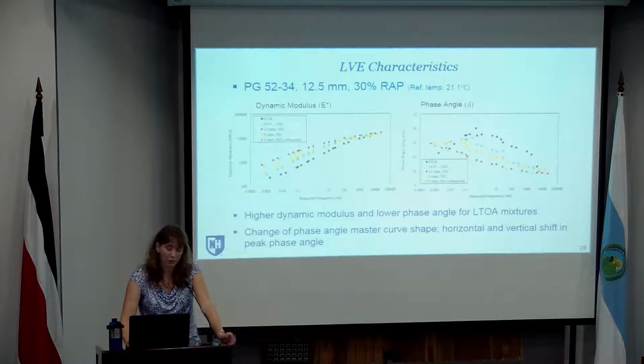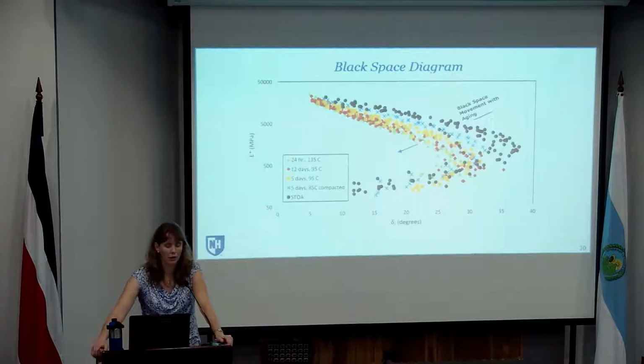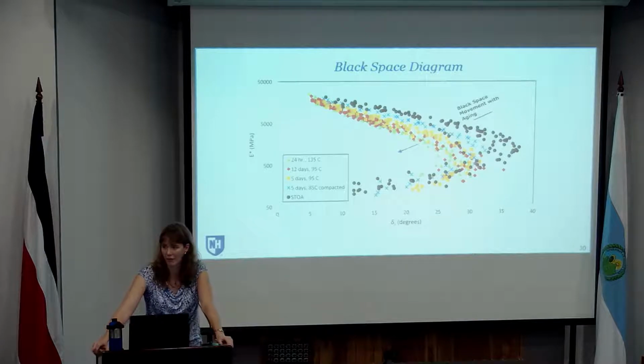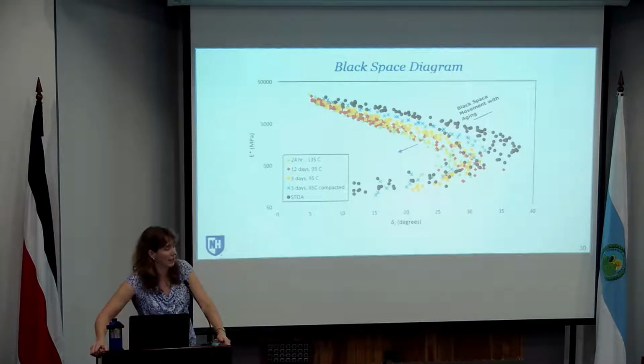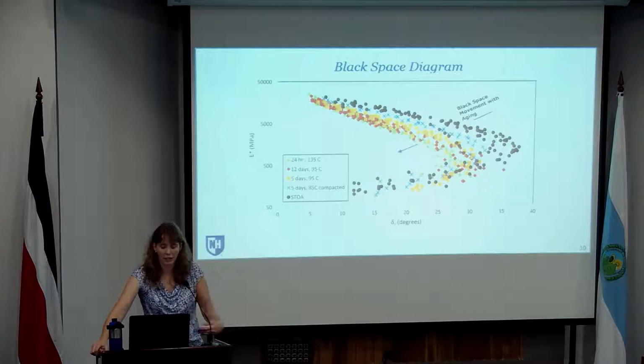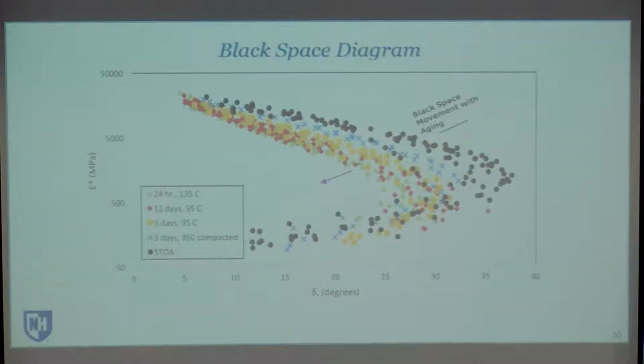So we looked at these individually, but you can also look at these in black space, which is really cross-plotting the stiffness with the phase angle. So that gives you a little bit of a different picture where you can look at the combined effects of the stiffness and that relaxation capacity. Again, you're seeing the same thing, where you're seeing a decrease in your phase angle and the shift in where that peak occurs, as well as an increased stiffness with the different aging. So it's just a different way of looking at it.